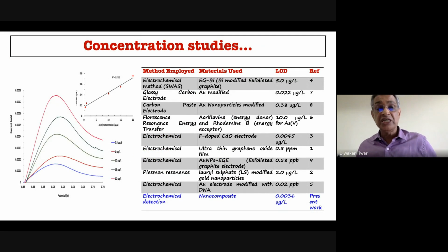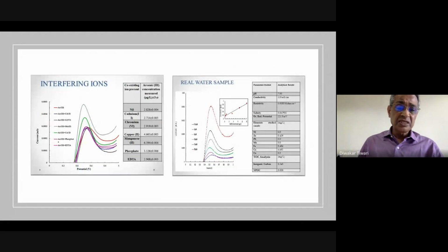So with this basic data, we tried to obtain the calibration line, varying the concentration of arsenic 3, and through that we obtained the LOD value, and the LOD value is significantly low. The LOD value that we could get is 0.0036 microgram per liter, that is almost the ppb level. As we know, 50 ppb is the permissible level, but with the help of this electrochemical system in the laboratory we could get 0.0036 ppb level.